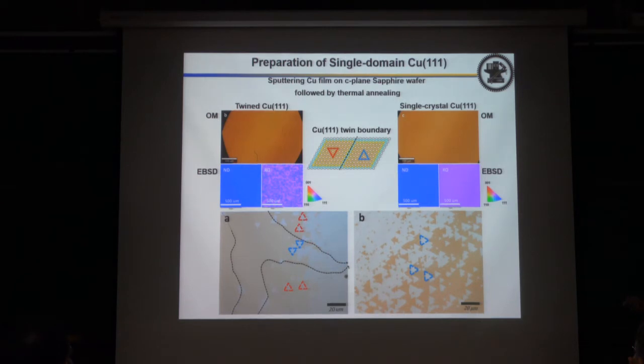they typically form the so-called two directions. For example, they have this direction and also another direction. So this is a grain boundary of the copper. If you prepare a copper substrate that is not single crystal, you will have many different grain orientations, and eventually you cannot form a single crystal up to wafer scale. So the key is how to prepare a single crystal copper (111).